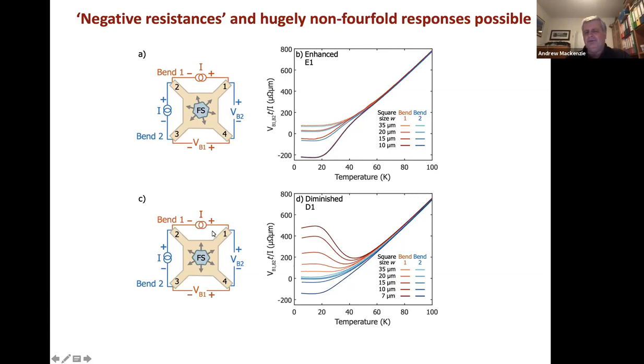However, if you do the same games in the diminished orientation, you see something similar at 100 Kelvin when you're ohmic, but you see something completely different at low temperatures, because there the vital symmetry that made that current injection orientation equivalent to that one no longer exists. So while you go negative for the voltages you see in the ballistic region for one of the current orientations, in the other one you go pronouncedly positive. So you've got rather a nice voltage anisotropy caliper that you can use to scale the size of ballistic effects.